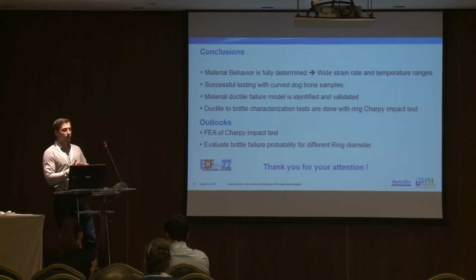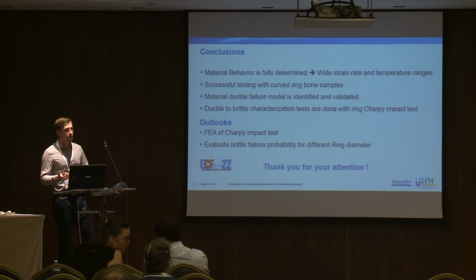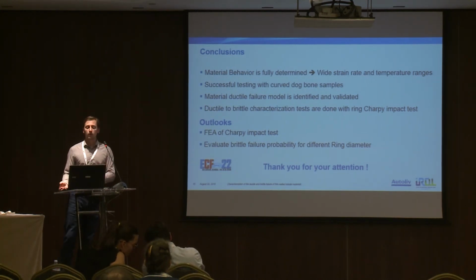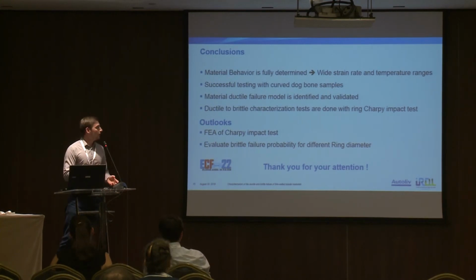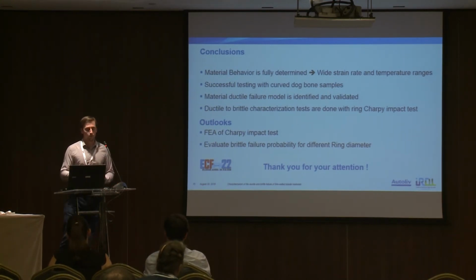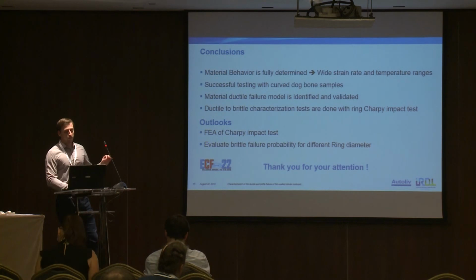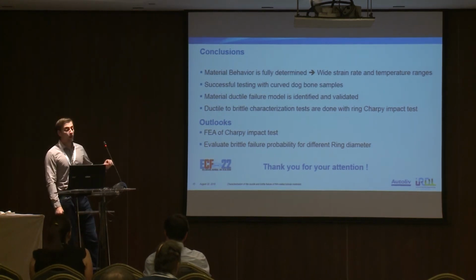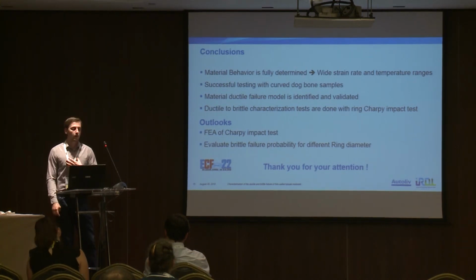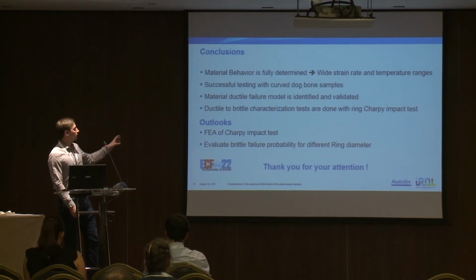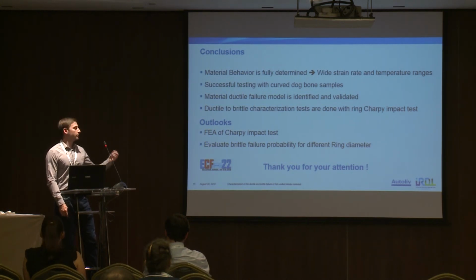First of all, I have to say that the material behavior is fully determined using wide strain rate and temperature ranges, and also for tubular material. Then, for the ductile failure, the model is fully identified and validated. So this is quite good for our industrial partner and for us, because it allows us to start the ductile to brittle characterization study.